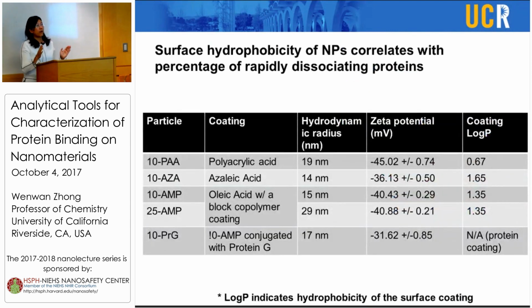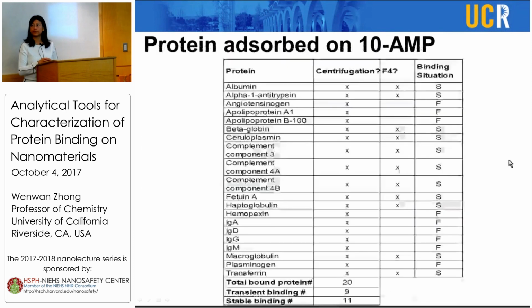So here again, to summarize the properties of these particles, the zeta potential measurements show that they are negatively charged with relatively comparable zeta potential, and their hydrodynamic radius is around 15 to 20 nanometers, and for the 25 they have close to 30 nanometers. And the log P value, as I said, is the index for hydrophobicity, right? For azelaic acid, which has the larger hydrophobicity, the log P value is 1.65, and PAA is the least hydrophobic, so it has the smallest log P value, which is 0.67. We use the chemical structure to calculate this log P value.